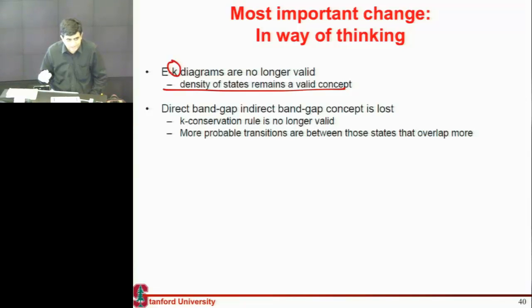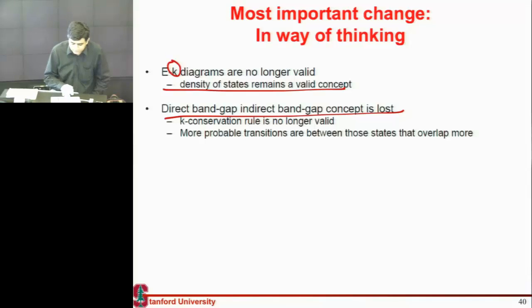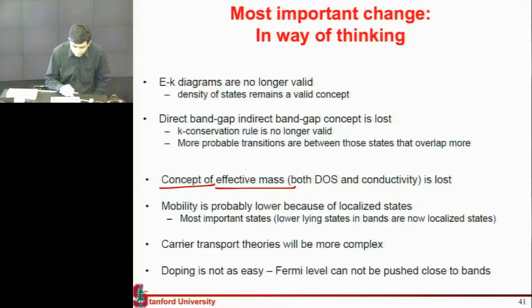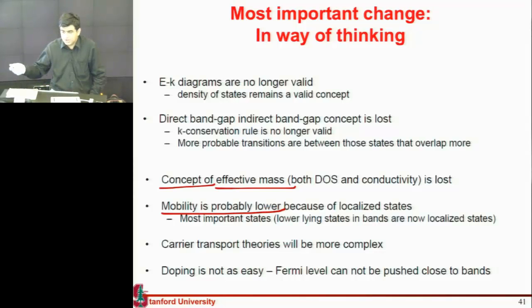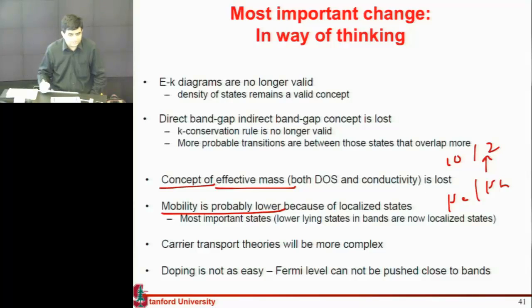Density of states thankfully remains a valid concept. You need two things: a density of states bottleneck and a selective contact — and a density of states bottleneck is available, so you can still make a solar cell out of these. There's no concept of direct band gap or indirect band gap, no crystal momentum. The concept of effective mass is also no longer valid. Mobility can still be used, but the mobilities in these materials are much lower — for example, mobilities of electrons and holes in amorphous silicon are around 10 and 2 cm²/V·s, versus hundreds or more in crystalline silicon.